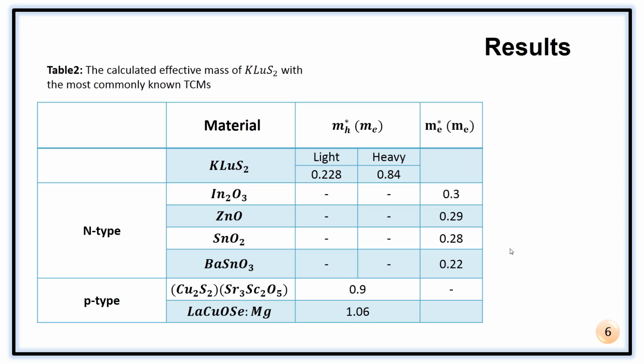However, this material has heavy and light Hall effective masses. The light effective mass is equal to 0.22, which is competitive with the industry standard P-type TCM, while the heavy Hall effective mass is equal to 0.84. In fact, this value is superior to some of the top performing P-type TCM materials.